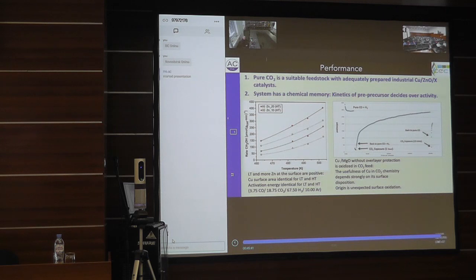How does this work? This is interesting. It's still copper in both cases, and it's written in the literature that copper is the active phase for CO2 hydrogenation as well as for CO hydrogenation. So why is there this strong poisoning? When you have copper on magnesium oxide, it is impossible to work with CO2, even with traces. If you have copper on zinc oxide, you must be careful to have more than 10% of CO2 in it, because otherwise the catalyst also dies. Operando spectroscopy is the tool to answer this question, and the interesting finding is that indeed, under working conditions, the catalyst surface is partly oxidized.